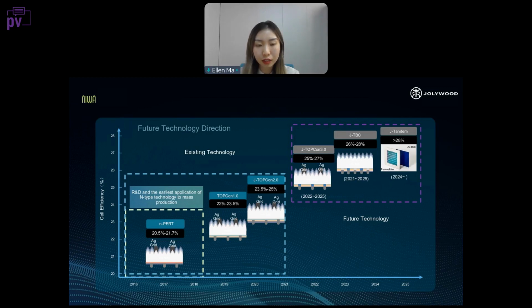But at this stage, we found out that the LPCVD technology will cause the polysilicon wrap-around. And we found our new solution, the TOPCon 2.0 technology. So right now, all of our products adopt the 2.0 technology, which can give you a maximum efficiency of 24.8%. And the Jolywood R&D team continues working on increasing the efficiency of solar cells. As I mentioned before, this year our TOPCon 3.0 technology, which is still in the lab stage right now, has a new world record efficiency of 26.1%. But this technology is still in the lab stage, though I believe it will come to mass production soon. And in the future, we will have JTBC and JTOPCon to continuously give our customers higher-efficiency solar modules.